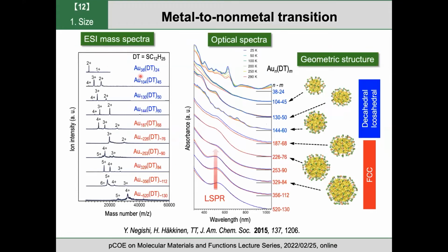So let me start with the size effect. As I told you, we can synthesize a series of clusters by the method. And here is the mass spec of the dodecanethiol-protected gold clusters, starting from 38 up to nearly 520. You can see the clusters are atomically precise. And we measured the optical absorption spectra of these clusters, and you can see here that the localized surface plasmon resonance at 520 nanometers disappears when we go from 187 to 144.